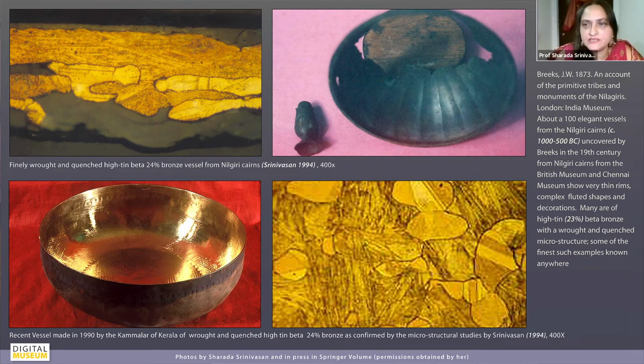It's really the microstructural analysis which helps you to piece together how the technology of how the artifact was made. In this case, the microstructure shows you very clearly that it's this wrought and quenched beta bronze, because you see this needle-like beta phase, which you would not see if it was not quenched. And it's quite extensively hot forged and then quenched, you know, the cycles of annealing, hot forging and then quenching.